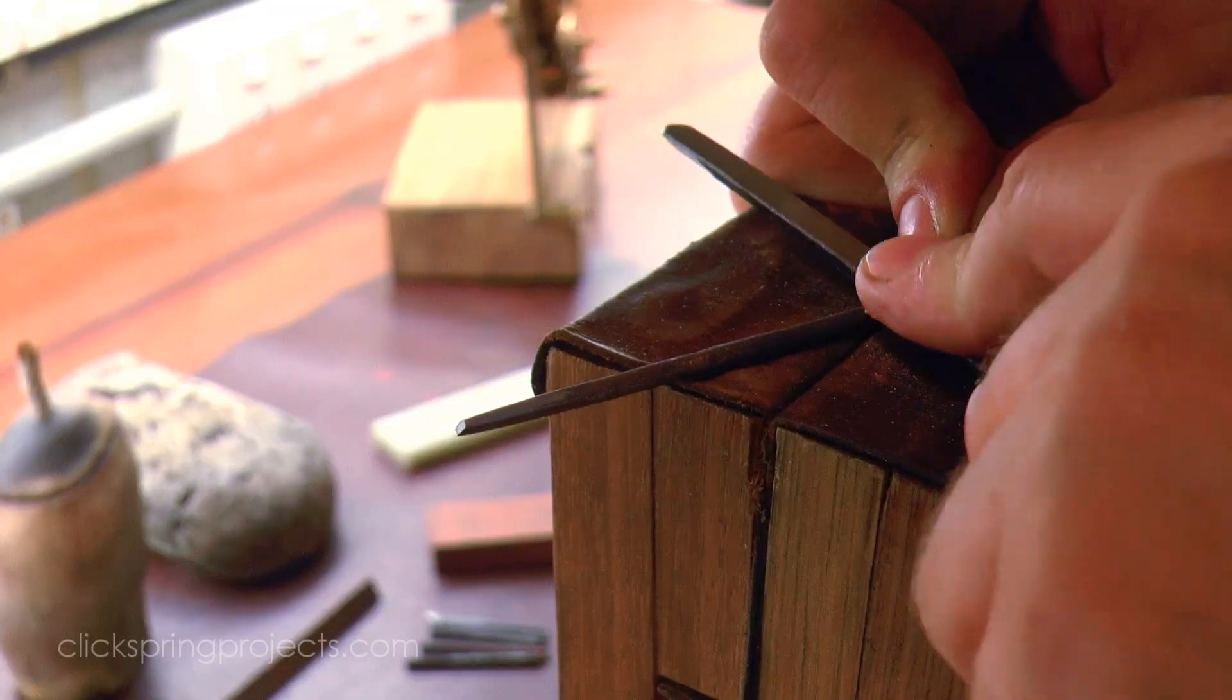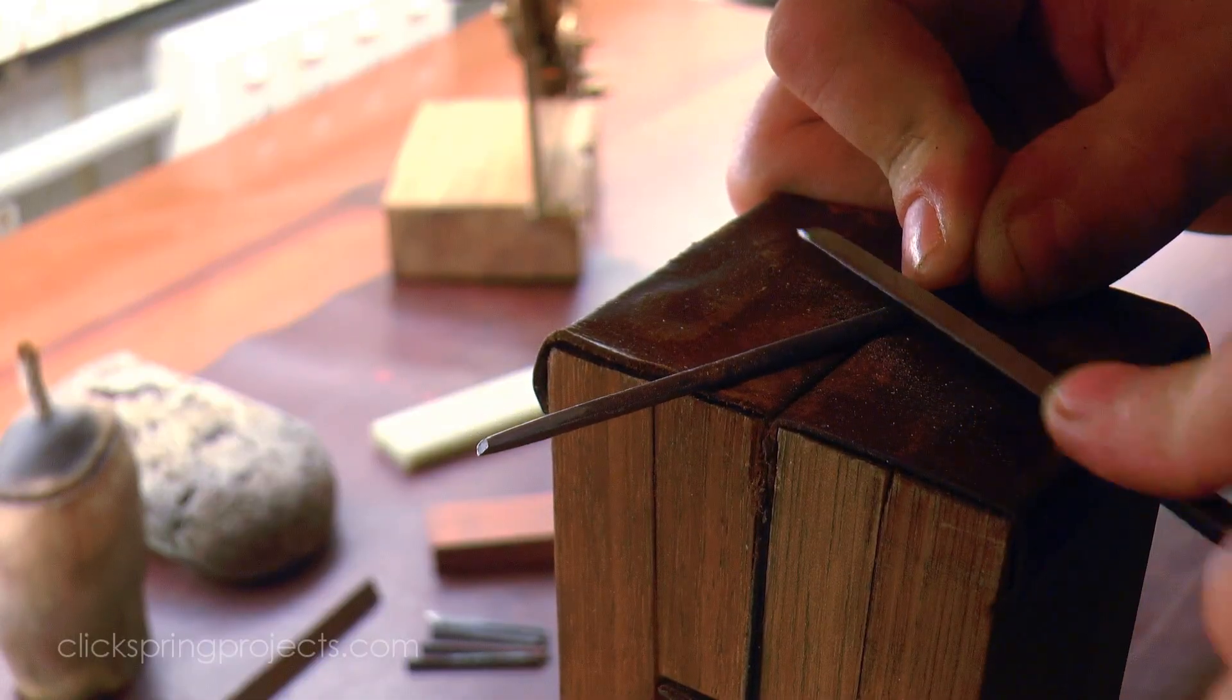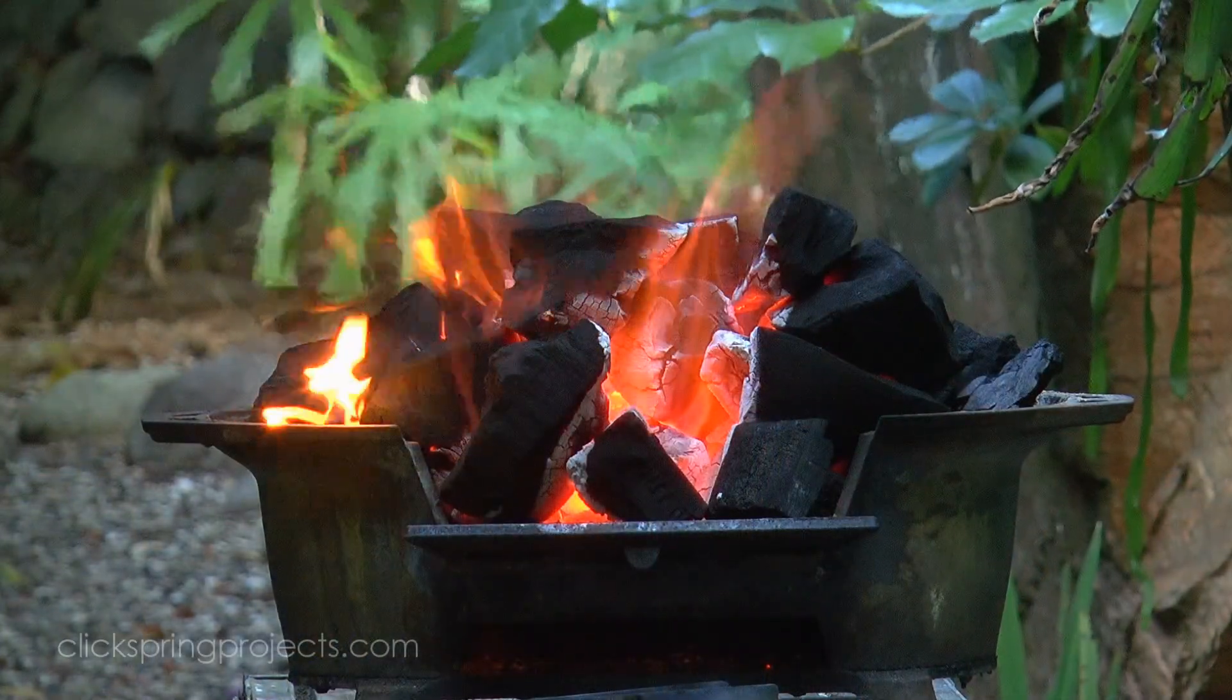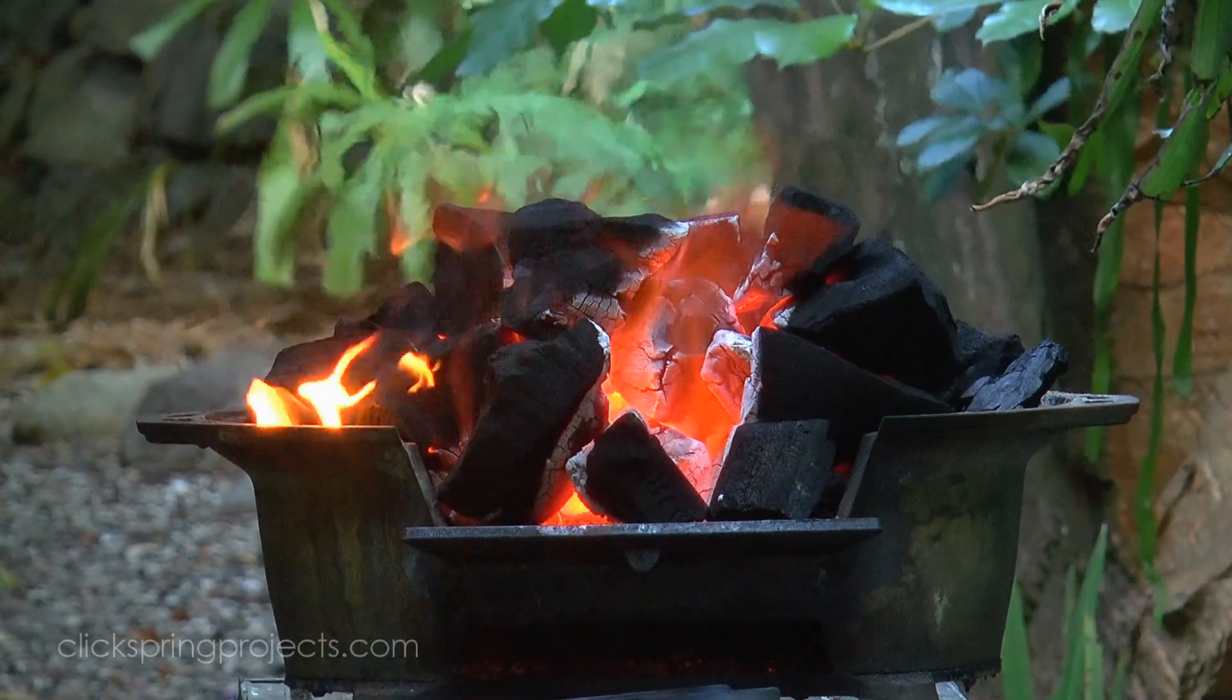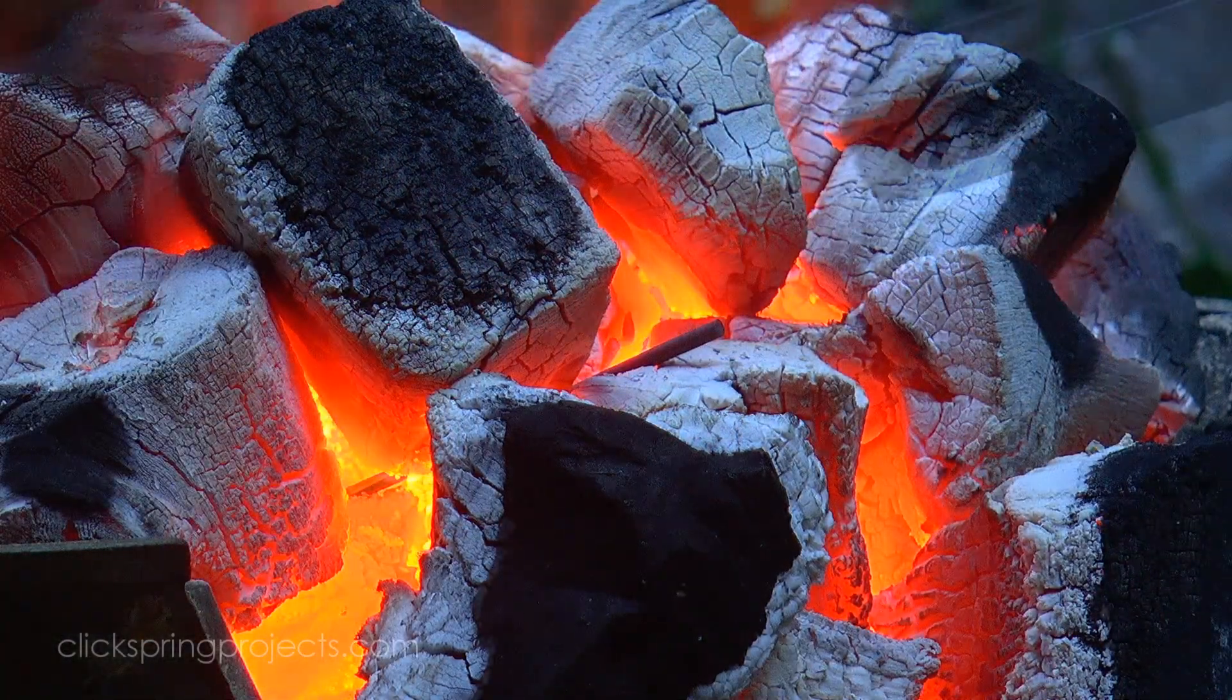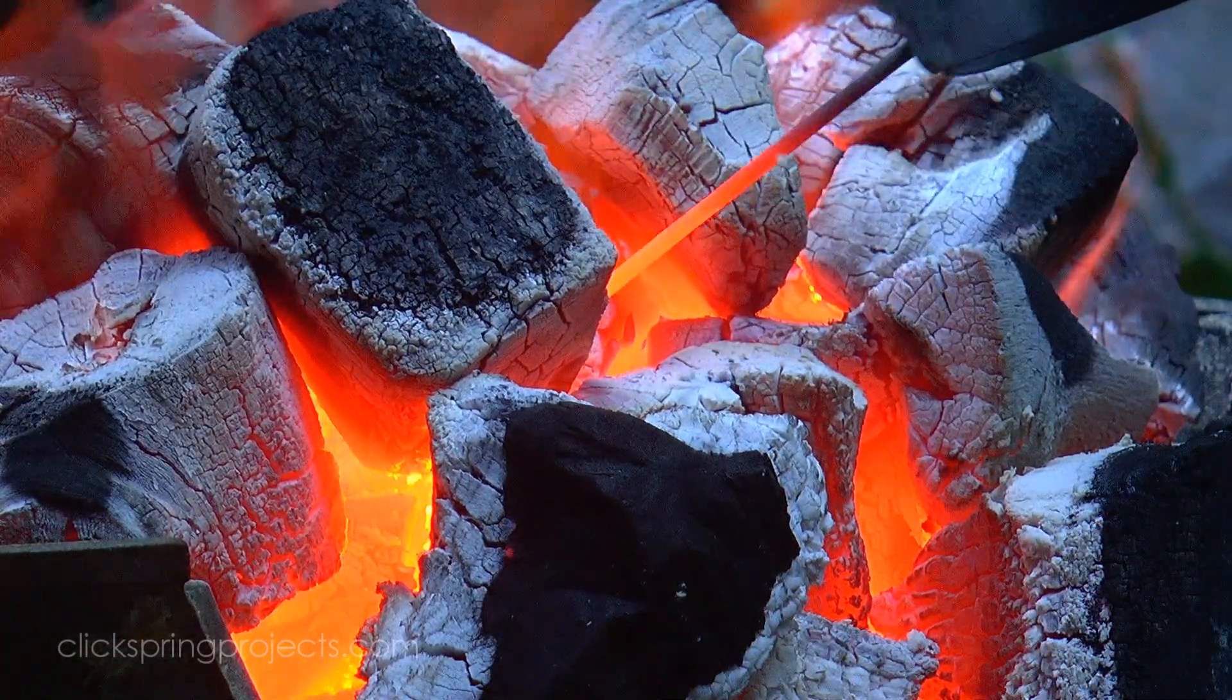In this case I formed a roughly 90 degree v-shaped cutting edge with a slight taper towards the cutting face. The material is then taken to a red heat and quenched again to transform it back into martensite.